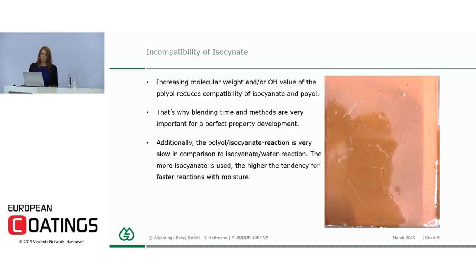So what you can see on the picture is kind of stripes plus foam. This is basically isocyanate penetrating to the surface because it isn't fully compatible with the polyol. And that can cause various kinds of side effects. So some people see that as fish eyes or think it's a defoamer problem, but it is a problem between the polyol and the isocyanate.